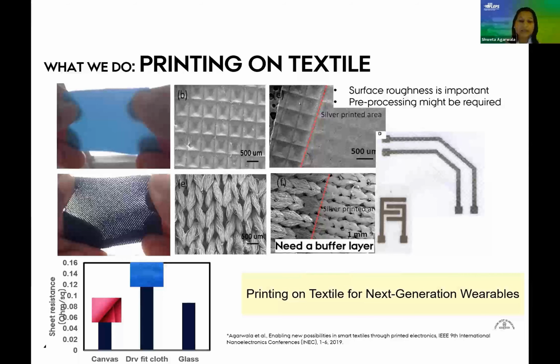sticking to your surface. What came out of this study is a very interesting fact, which was that some of these inks adhere very well to some of the surfaces or textiles in a way that enhances the functionality. So if I were to print the same material on a glass or a plastic, they might have a certain, for example, sheet resistance or conductivity, but that gets enhanced when I put the same material on a textile.